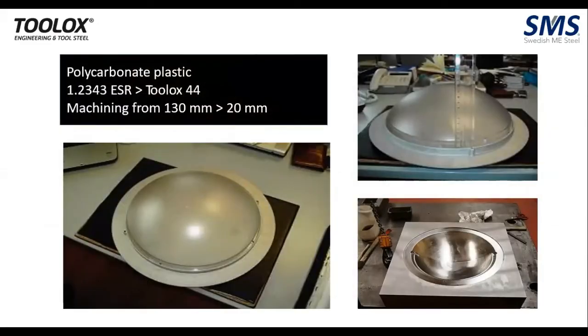Here is an interesting thing. The material being molded is polycarbonate plastic, but you can see that the machining was done with Toolox 44 from a 130 mm block, with the inner depth going up to 20 mm for this kind of thing. Throughout the block, what you have is a through hardened material. So it's not a question of the hardness reducing as it progresses towards the center of the material. It is 45 HRC throughout, each and every corner of the material.